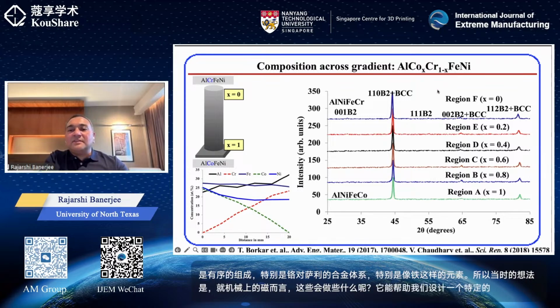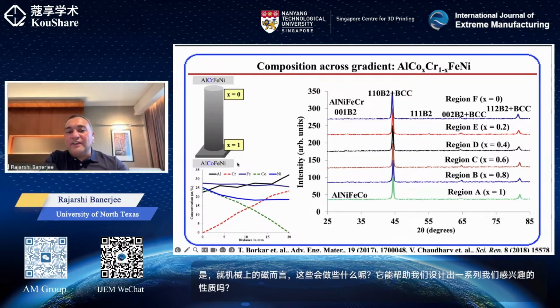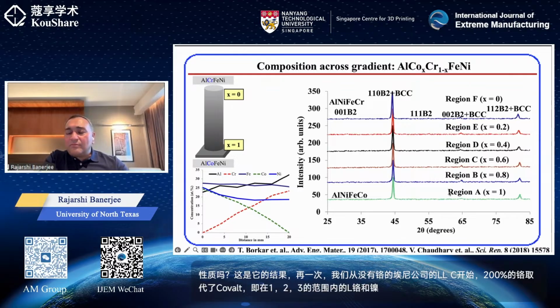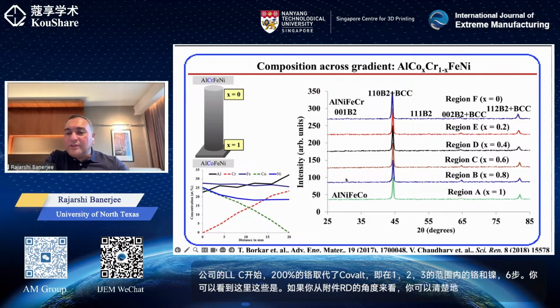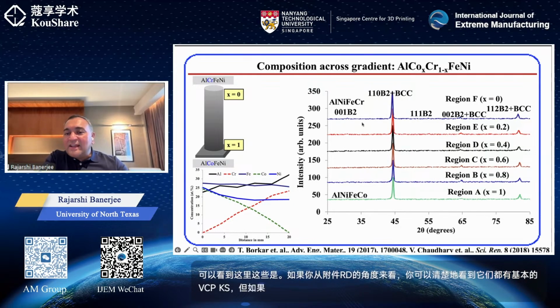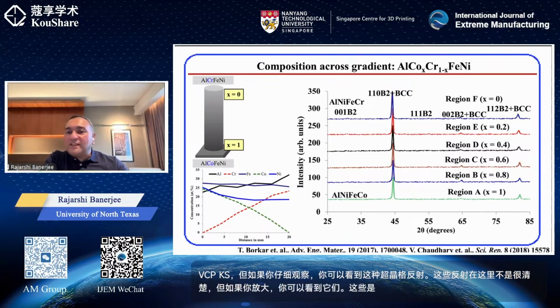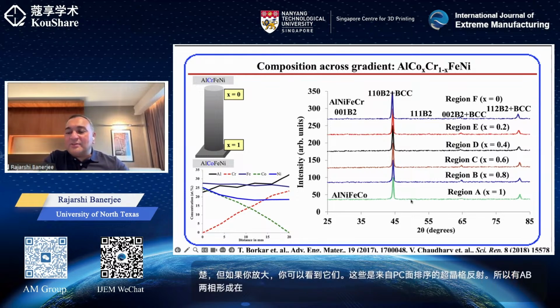So these are the results. Again, we go from AlCoFeNi with no chromium to 100% chromium replacing cobalt, which is AlCrFeNi, over a range of 1, 2, 3, 4, 5, 6 steps. So you can see here the respective compositions. If you look at it from an XRD point of view, you can clearly see all of them have fundamentally BCC peaks. But if you look carefully, you can see these superlattice reflections arising. These reflections are not very clear here, but if you zoom in, you can see them. These are the superlattice reflections from ordering in the BCC phase. So there is a B2 phase also forming in this system. And otherwise, it's pretty similar. You don't see a huge change, but this is only at the XRD level.